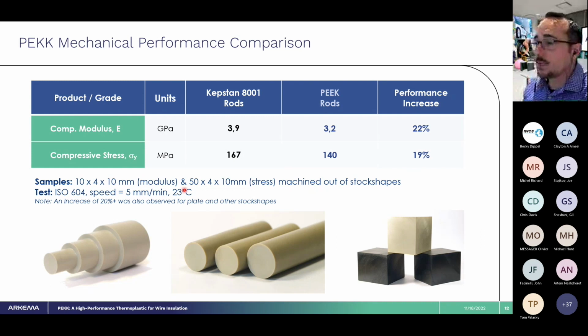This test is specifically at room temperature, machine samples out of stock shape. You can see for PEKK in this column, we have a modulus of about 3.9 GPa and a compressive strength of about 167 MPa. Whereas for PEEK, you're going to see a modulus of about 3.2 and a strength of about 140 MPa.